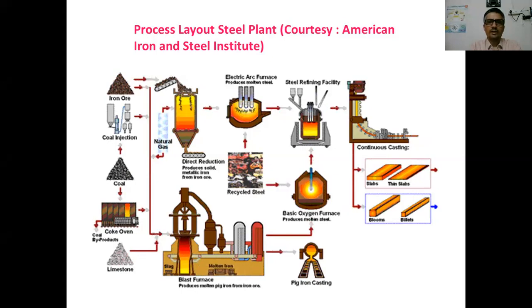And then for primary steel making, also there are two prominent processes. One is the electric arc furnace, which by and large consumes solid charge, that means scrap and DRI, and the basic oxygen furnace, which consumes 70 to 80% liquid pig iron, followed by solid charge consisting of scrap and DRI. And the end product of both goes to the secondary steel making stage.